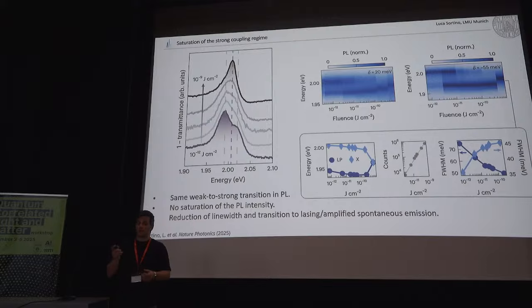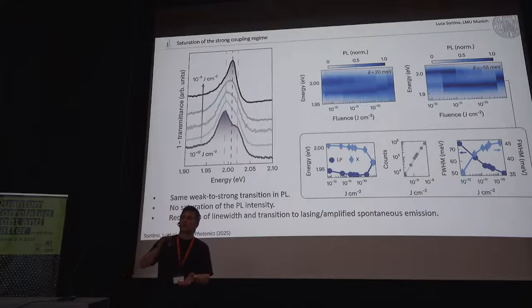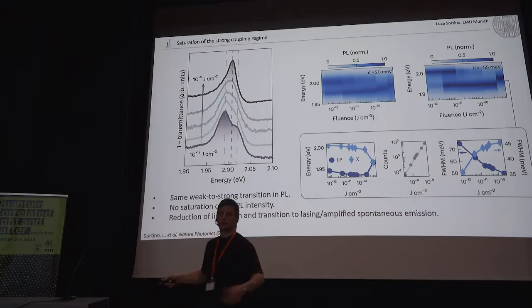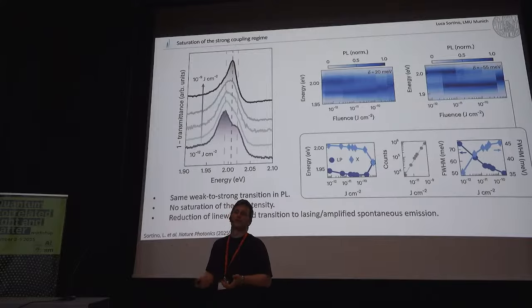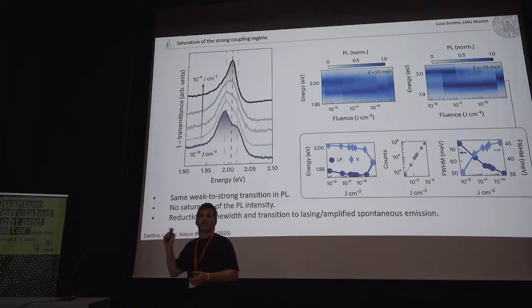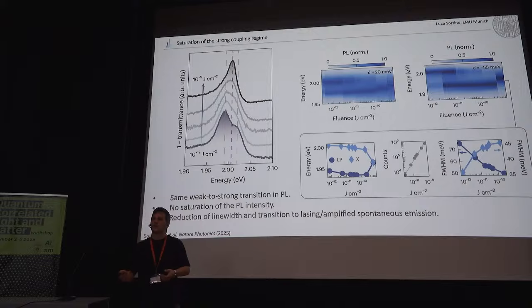Yeah, absolutely. But one thing that I completely forgot to say is that these powers are 3 orders of magnitude lower than every other system of 3D material. If you take your microcavity DBRs, the saturation, the lasing thresholds, and everything that has been said or observed is 3 orders of magnitude higher in power, because in most of the works you use some kilohertz excitation. Here we're using 80 megahertz, and on large spots, so the powers themselves are extremely small. All right. So there shouldn't be this strong mode insulator and so on.